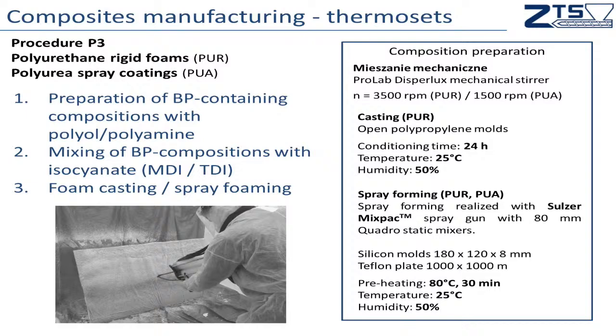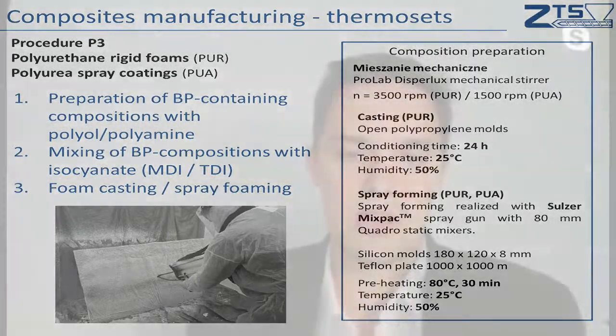Using basalt powder as a filler for polyurethane and polyurea spray coating composites. Actually, we have just finished a quite big project with our local industrial partner, and we prepared composites containing basalt powder as a filler for the materials that will be used for spray coated reinforcement of pipes for water supply. Usually we incorporate basalt powders into the polyol or polyamine. We prepare the mechanical mixing, and after that, depending on the preparation method, we use a static mixer and spray coating, as can be seen below.